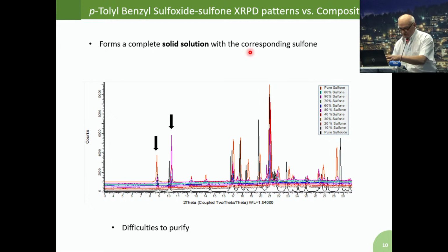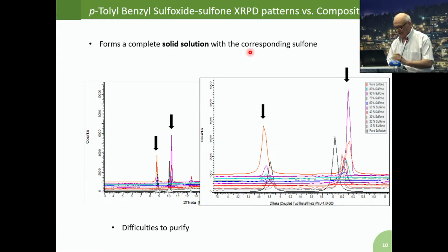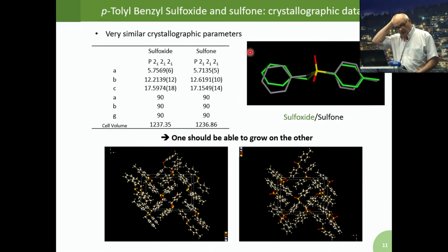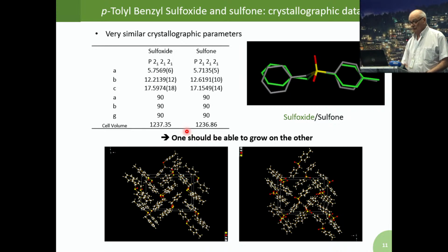And indeed, if we concentrate on the two peaks which are spotted here, we can see that we have a continuous evolution of the parameters, and indeed we have a complete solid solution. So this is why we adapt the synthesis so that we don't have this sulfone inside the crystal lattice. And then when we look at the complete crystal structure, we were not surprised to see the same space group, very similar parameters, and if you look at the volume of the unit cell, it's almost the same, which confirms that the lone pair of a sulfur atom is almost as bulky as an oxygen. And looking at the projection of the crystal structure, you can see that they are almost the same.